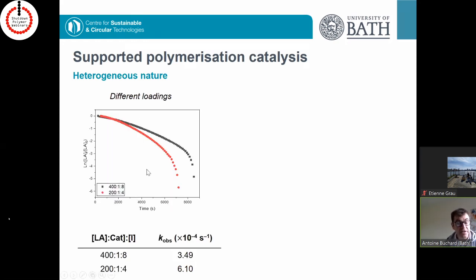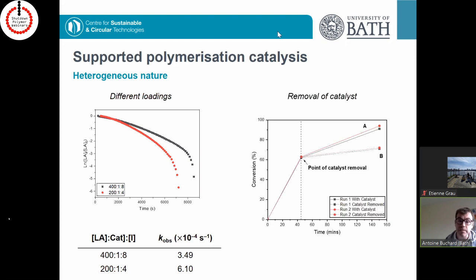When we were decreasing the amount of beads, we also had a reduction, almost as expected, of the rate constant, which indicates as well that it's likely to be heterogeneous. And most importantly, what we did is we removed the catalyst right in the middle of the reaction, which was actually a bit tricky to do, because remember that we were doing this in really hot molten monomer, and this was quite tricky.